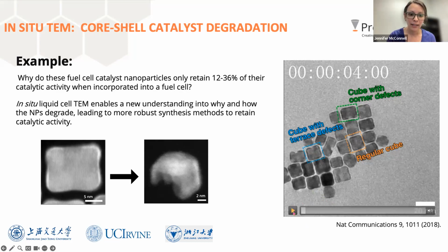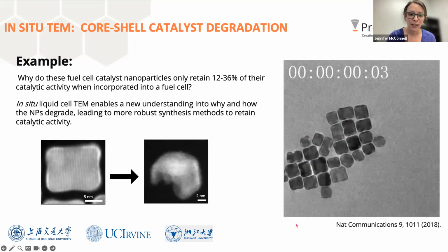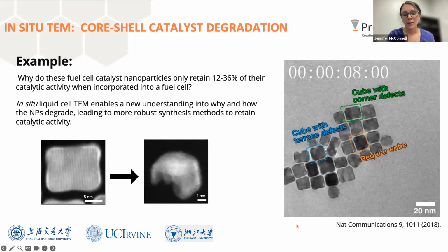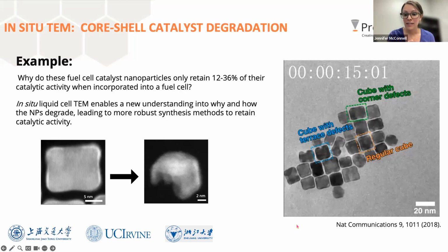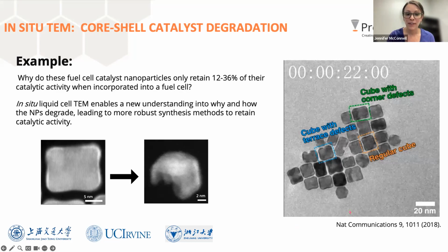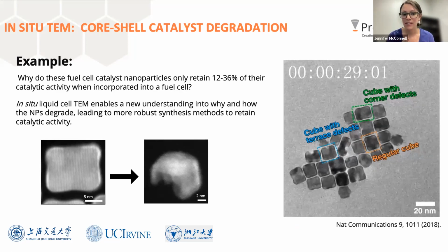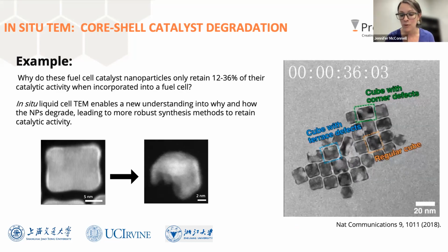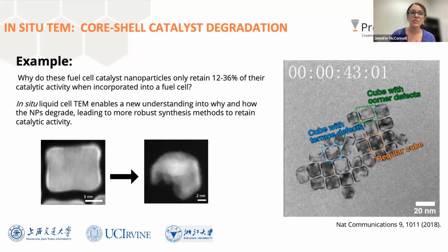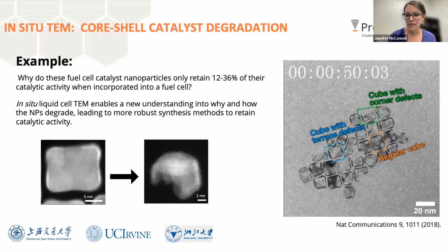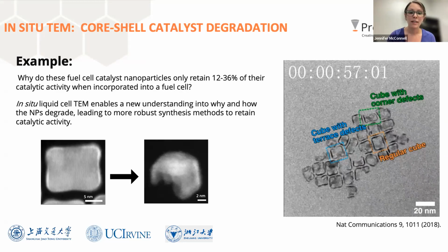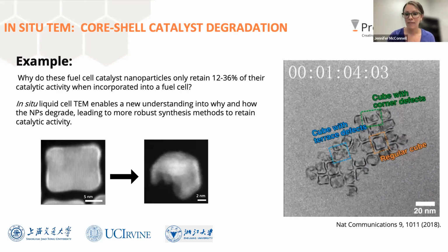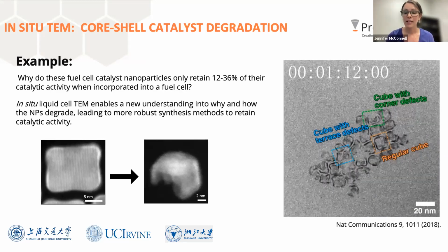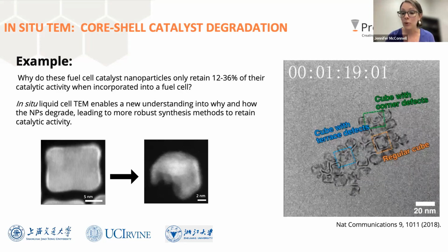And so you can see the particles here. You've got the particles, and several of them have defects. You've got terrace defects, you've got corner defects, and then they also outline one that doesn't have a defect. And as they use the beam to apply stress to watch the breakdown process, the etching process going on here, it becomes very obvious that these defects have a huge impact on how quickly these particles degrade.